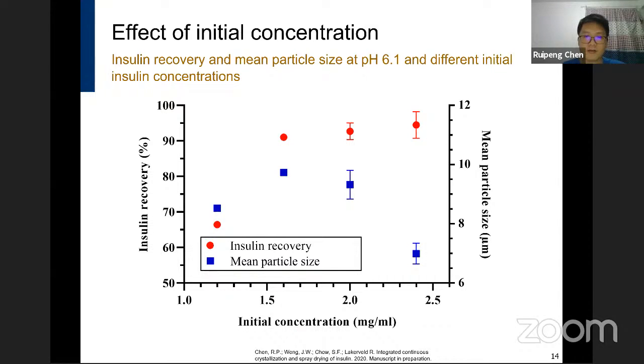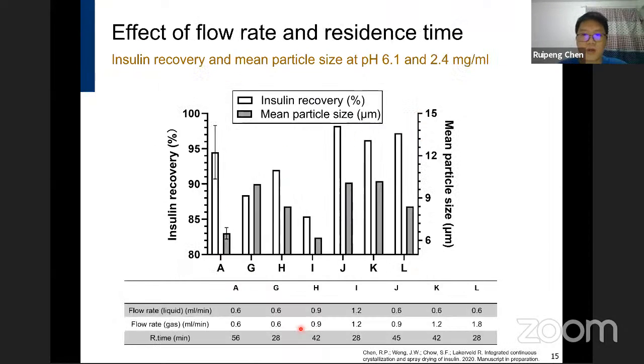And then we studied the effect of flow rate and residence time on these two quality attributes. Now there's a lot of information in these slides. I just want to point to a few general conclusions. You can see for all these conditions operated at the same pH and initial concentration, but with different flow rate and residence time, they all achieve a recovery of over 85% and even 90%.